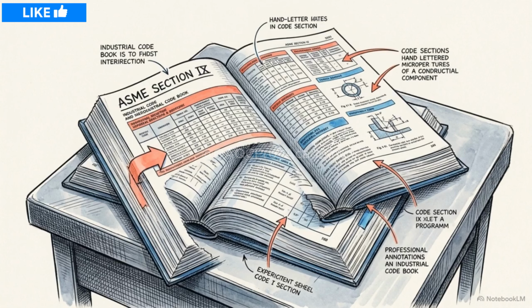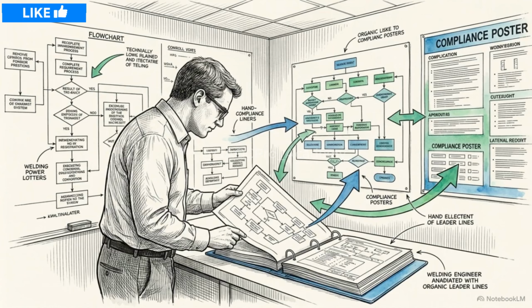Non-essential variables are parameters that do not impact the physical properties of the weldment, such as a minor shift in travel speed. Adjusting these requires only a paperwork revision to the WPS. Essential variables are parameters that dictate mechanical integrity, such as the base metal P number or the welding process itself. This AWS D1.1 WPS Essential Variable Checklist shows thresholds for process parameters and filler metals. Changing an essential variable beyond limits requires an entirely new PQR test. Further down, supplementary essential variables activate when the code mandates toughness testing, turning flexible parameters into strict limits. Identifying these variable thresholds prevents a minor administrative change from turning into a mandatory physical requalification.